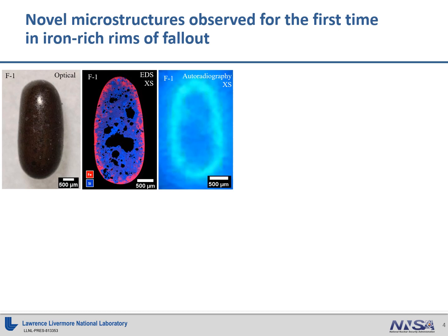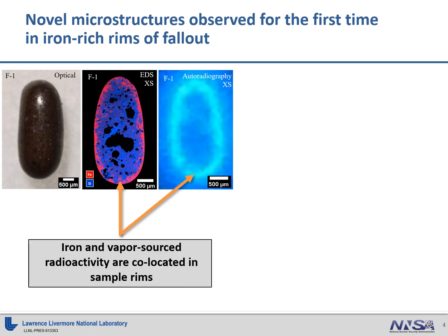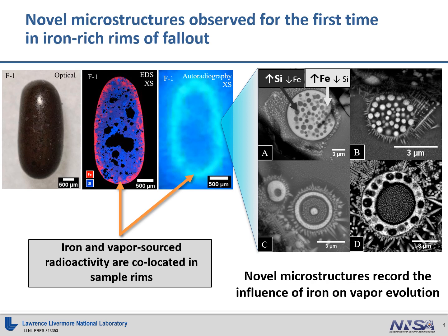Cross-sections of glass beads revealed rims with a co-location of residual radioactivity and high iron concentration, suggesting these regions are sourced from an iron-rich radioactive vapor. Investigation into those rims reveals a wide variety of never-before-seen microstructures, including these complex micron-scale spheres of varying morphologies, but with a distinct two-phase structure. One phase consists of a high iron and low silicon content, and the other is high in silica and low in iron content.